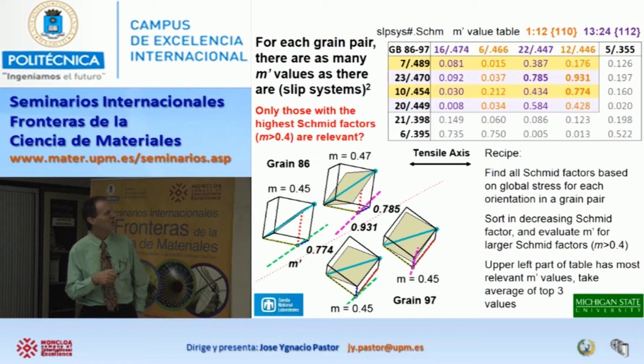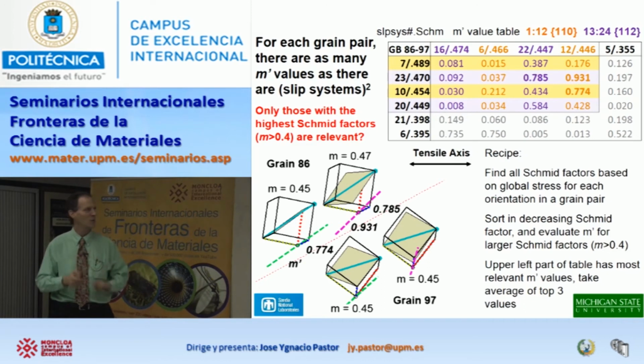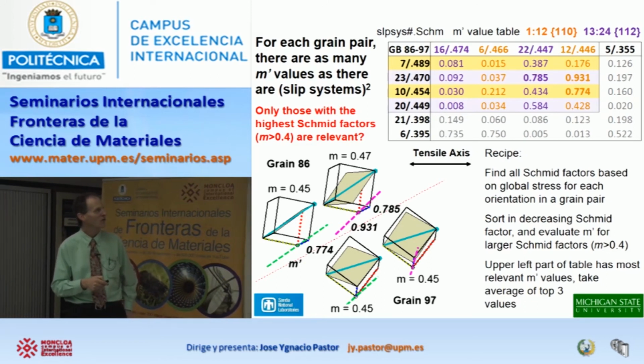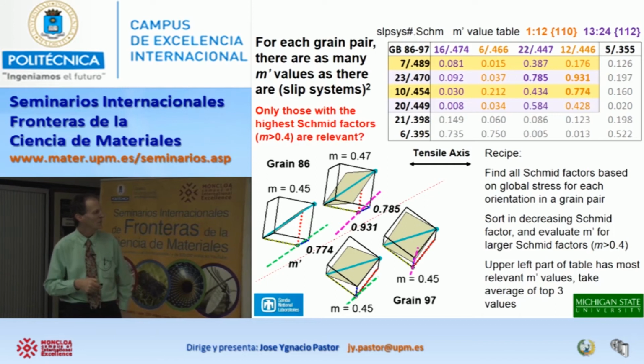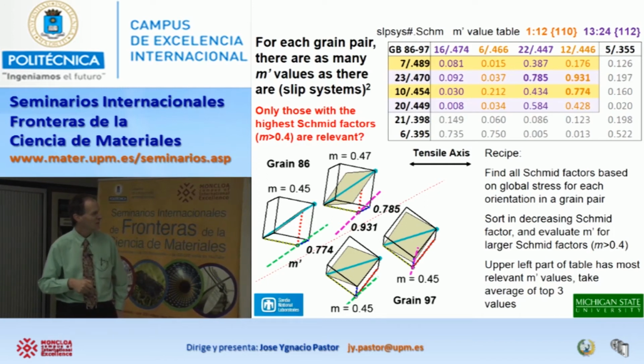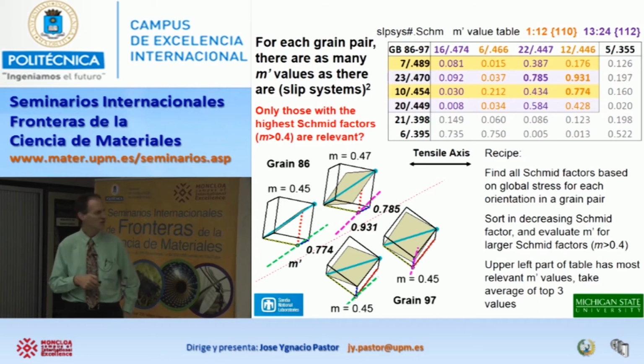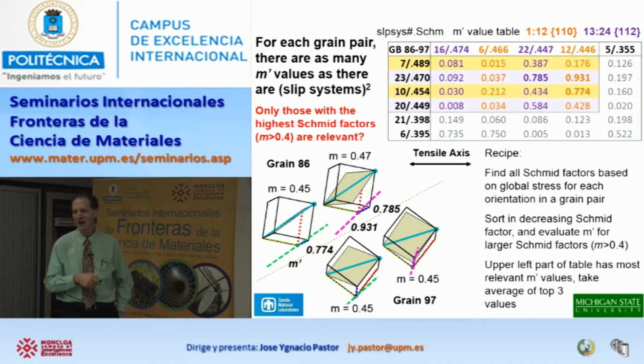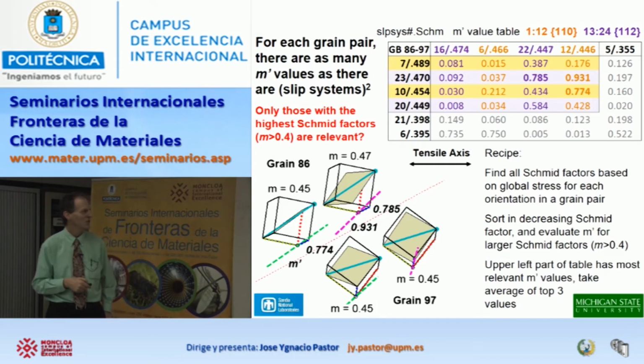For each combination of slip systems which I would expect to be active, or at least potentially active, I can work out what this M prime parameter would be between them. In most cases, they're really small, which means they're not well lined up at all to transfer slip across the boundary. But there are three of them that are somewhat larger right here, and they're illustrated here. If I consider this slip plane with this Burgers vector direction, and this slip plane with that Burgers vector direction, they're lined up with a value of 0.93, which is not perfect, because you can tell they're not perfectly lined up, but they're close. So that's probably the most likely slip transfer opportunity.